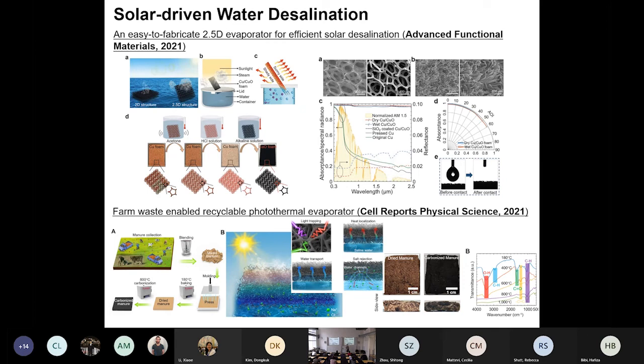And people might ask me whether I worry about some bio stuff, bacteria. Clearly no. After 600 degrees C, no bacteria can survive at this really high temperature. And also this material itself can survive pretty well in water. It will last a long time. We didn't imagine this case. We thought we might need to add some bonding material, adhesive, gluing material to bond those carbonized materials, but no. We didn't know the reason, but we found that if you simply let this material float at the water interface, it lasts as long as it can. You won't see any part falling apart. But we did find an issue for other projects. We're going to see that next slide.